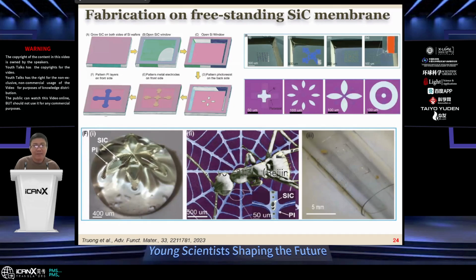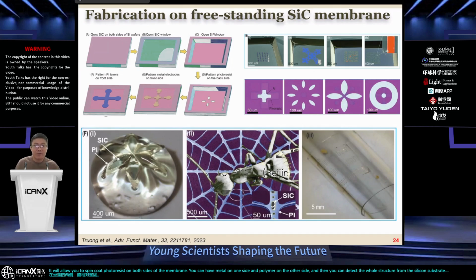And later on, we developed another fabrication technique that allows us to transfer random structures, not only through stamping, but by direct lithography on both sides of the silicon carbide membrane. The membrane is relatively strong. It will allow you to spin coat photoresist on both sides of the membrane. You can have metal on one side and polymer on the other side, and then you can detach the whole structure from the silicon substrate, like this silicon carbide on polymer flower.